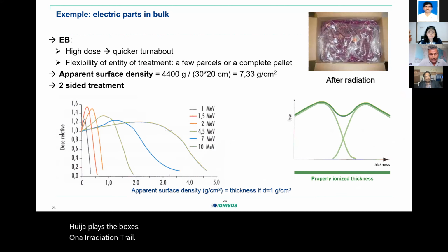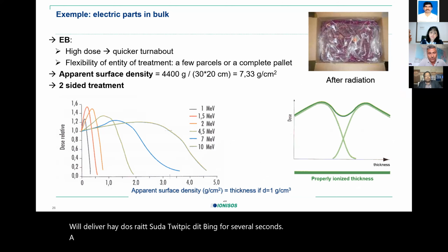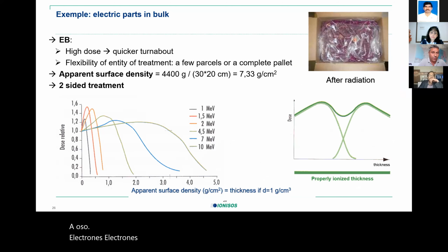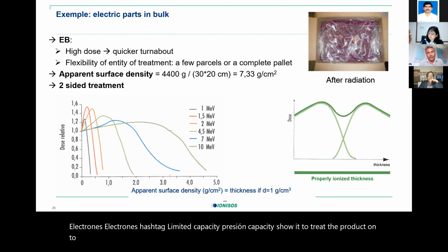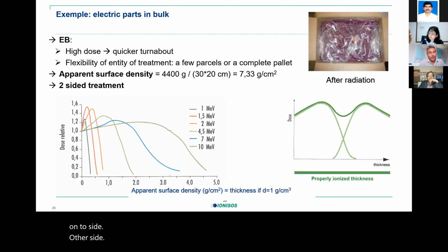We are using E-beam, as indicated before. As we said before, the E-beam will deliver a high dose rate, so that will make the treatment quite quick. This means that the product will be under the beam for several seconds. We are also treating with electrons. These electrons have a limited penetration capacity, so we will need to treat the product on two sides. This means that we will have to turn the product 180 degrees to be treated on two of its sides to have a complementary dose profile, as you can see in the graph. The dose will be a combination of those two passes.